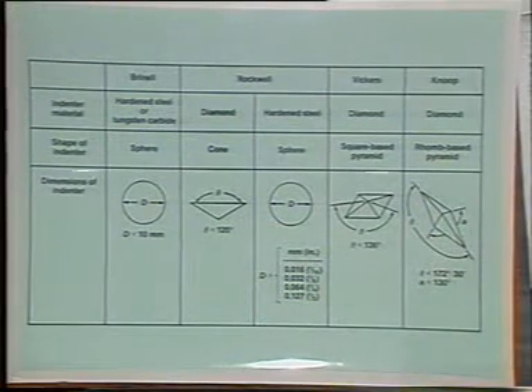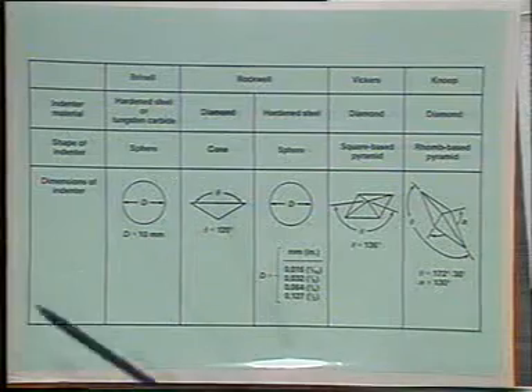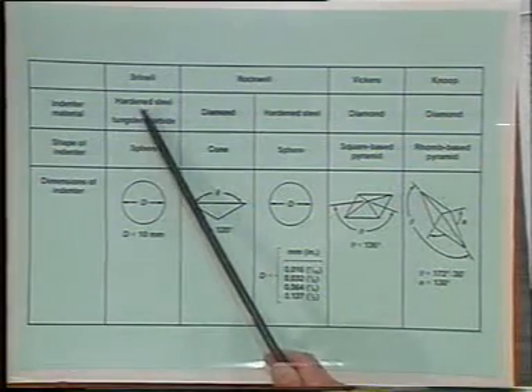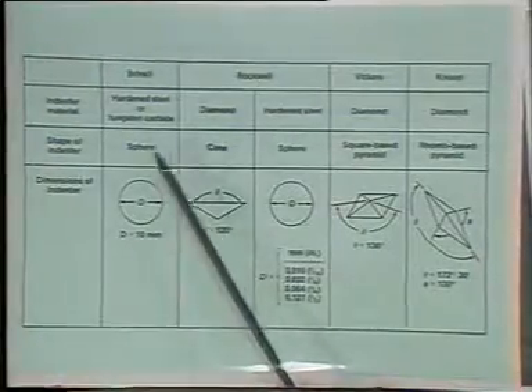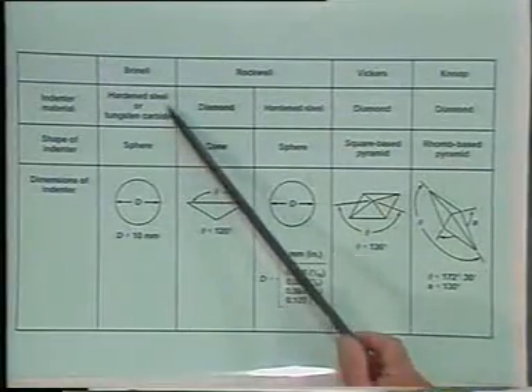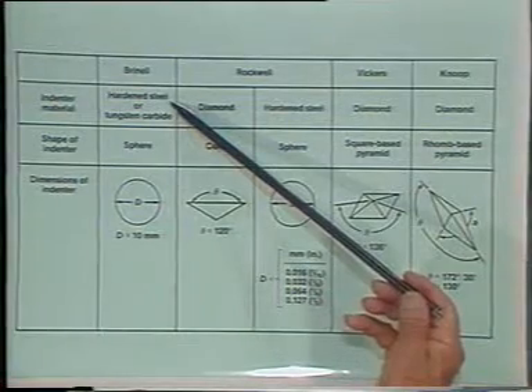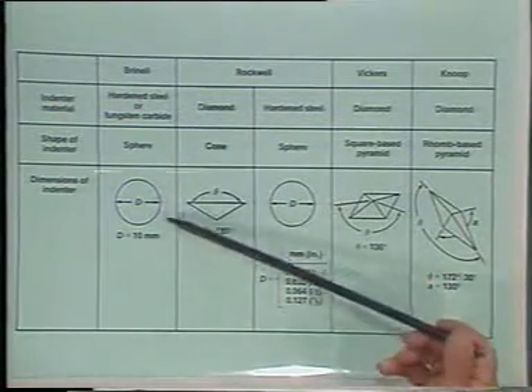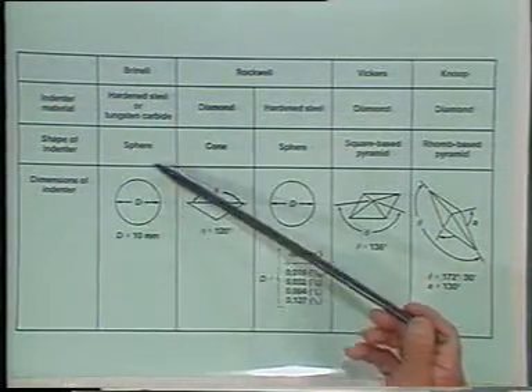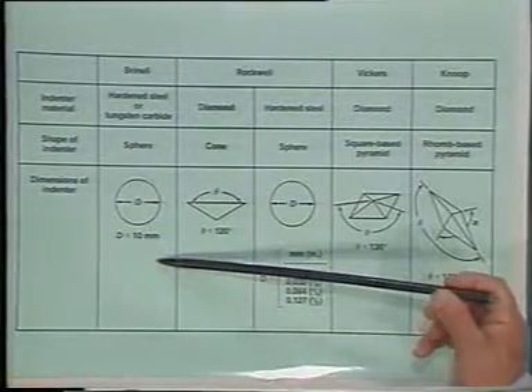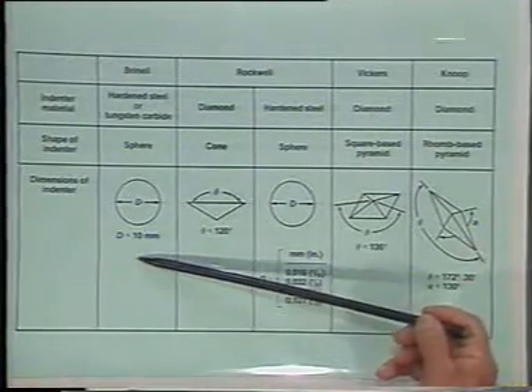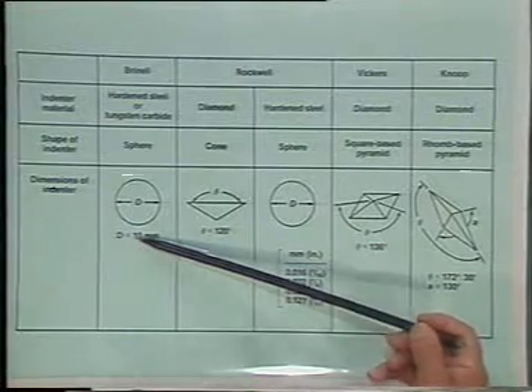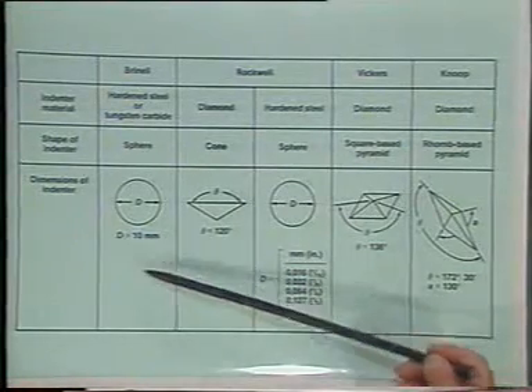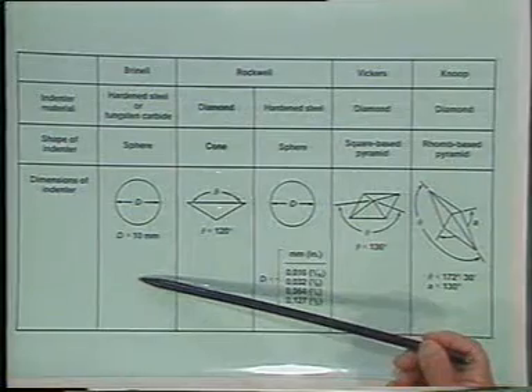And so we have a whole array of hardnesses that we use. And these hardnesses are the Brinell hardness number, the Rockwell hardness number, the Vickers hardness number, the Knoop number. And we have an indenter that's used in them. And let's talk about the Brinell at first. What we really use here is a hardened steel or tungsten carbide ball. It's 10 millimeters in diameter. It's spherical in shape. We load it over top of a specimen, if it's a piece of steel, with a 3,000 kilogram load, and it makes a dent in the specimen. And then we remove it, and we measure the diameter of the impression, and we can relate that to the ultimate tensile strength if it's steel.